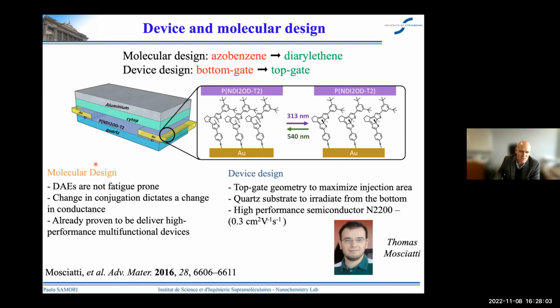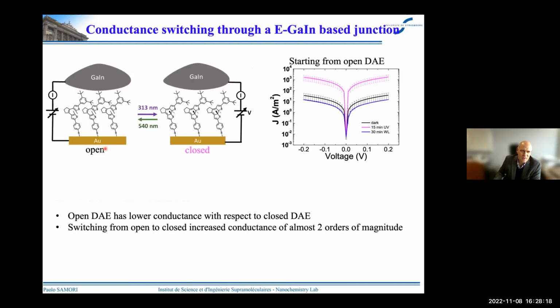On the other hand, the use of diarylethene instead of azobenzene means that we are dealing with a photoswitch that is not fatigue prone, and that it can be used to deliver high-performance multifunctional devices. So the first way to test the switch of our diarylethene is to embed it into a single molecular thick junction, in which, instead of the mercury drop, we use an indium gallium eutectic. On the right you can monitor the IV curves, and you can see that we have an efficient switch between the two states with a change of the conductance of almost two orders of magnitude.